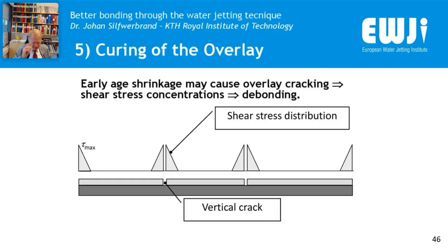Curing is also important, because early age shrinkage may cause some overlay cracking. And if you have some overlay cracking, there is a risk that you will have a concentration of shear stresses in the vicinity of the crack and also at the edges. And these shear stresses might exceed the bond strength, and then you could have a horizontal crack develop in the bond, which is called debonding. And this debonding process starts at the edges and at the cracks and develops to the interior parts.